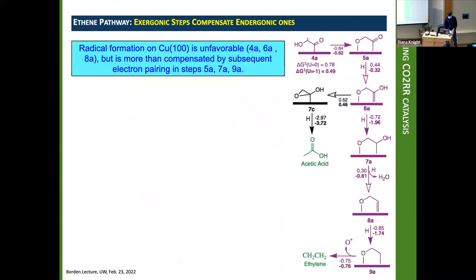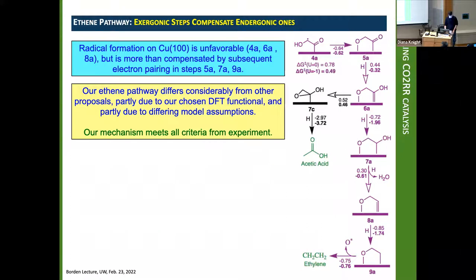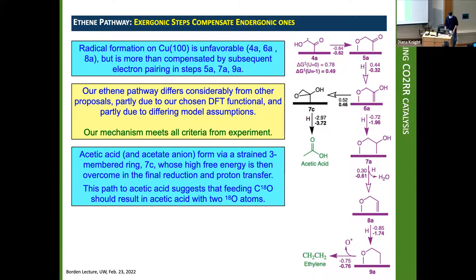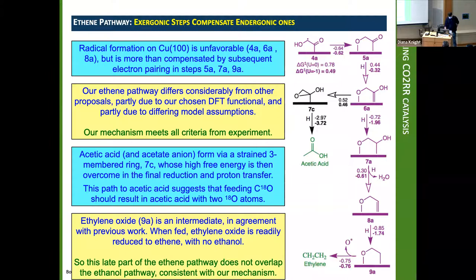The ethene pathway is quite interesting because it consists of alternating highly endergonic steps interspersed with exergonic steps. And so it's an interesting looking staircase. This differs considerably from other proposals. As we'll see in a few minutes, one of the fun things about working on mechanism in heterogeneous catalysis is you will be challenged. And if you're in the right frame of mind, those challenges can be fun. So we claim that our mechanism meets all experimental criteria, and amongst those is the fact that we can understand what goes on with acetic acid. We make an experimental prediction there. If you feed ethylene oxide, you get ethene. So all these pieces kind of hang together.